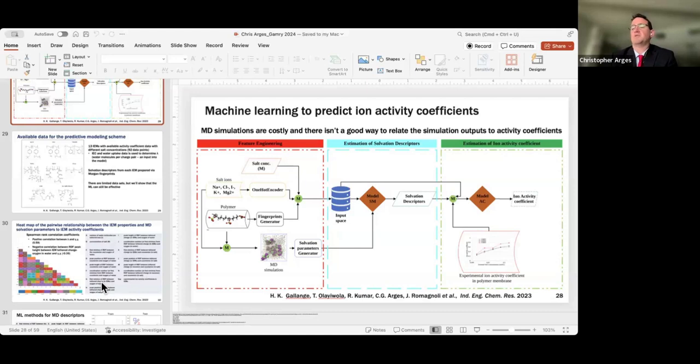My postdoc, who synthesized the polyterphenyl alkaline anion exchange membrane, I don't know how he came up with it, just let the cell sit with a phosphate solution overnight to ion exchange. And then the device worked much better for phosphate removal. So what we realized is that you need to ion exchange to the desired ion that you want to move before running the cell.